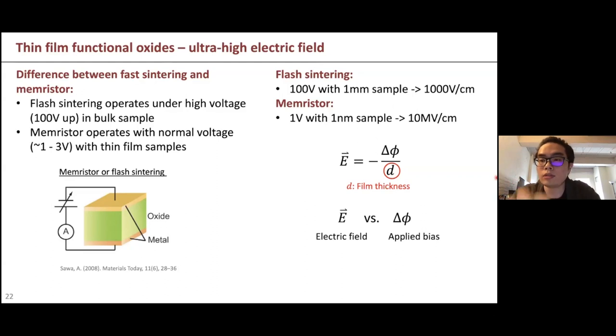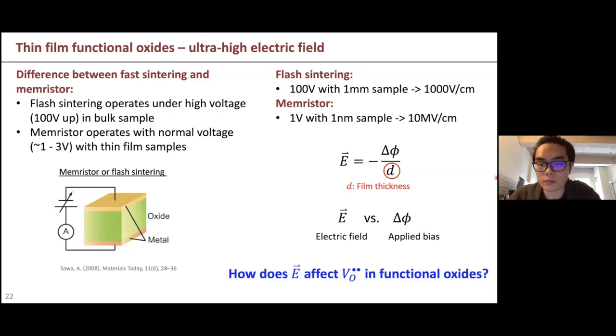Although these two physical properties, the electric field and the applied bias, are coupled together because they appear at the same time, they actually have different contributions and influences on defects. People already know to use the Nernst equation to understand how the bias can affect the oxygen vacancy in oxides. However, how the electric field affects the oxygen vacancy is still a question that we can ask.